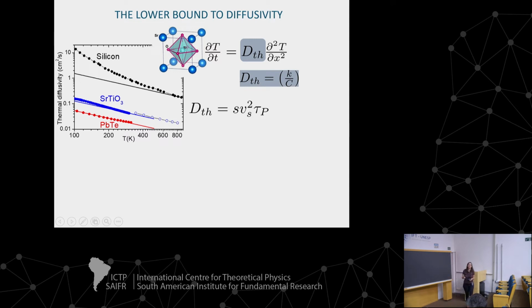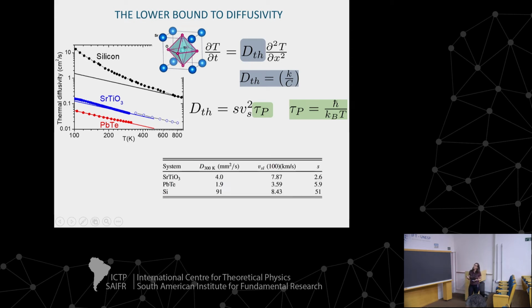We have observed that if we write the thermal diffusivity according to this equation, where S is a dimensionless number, then we have the square of the sound velocity, and tau p is the Planckian time. Why this equation? Actually, this was not out of the blue. This is used also in the study of bad metals. So inspired by this parallelism, we compared STO with other insulators, and we can see that S does not fall below 1.